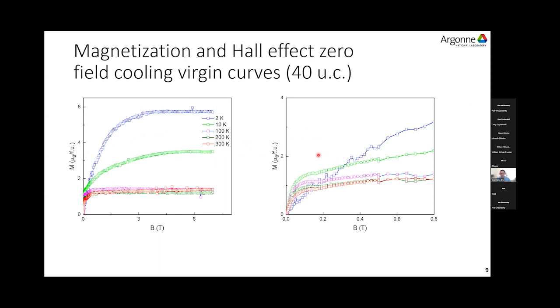And the difference from the Hall effect, which measures the manganese lattice only, is that the virgin magnetization curves could show magnetic properties in both the manganese and the terbium sublattice. The left panel is the virgin magnetization curve to 7 Tesla. And if we enlarge it, we could see there is a bump here below 0.2 Tesla. Before this bump, there is a sharp curve, and after it, the curve becomes flat. And the magnetization saturates slowly at higher fields. One conclusion we could draw here is that by zero field cooling, we could obtain a low magnetization state.